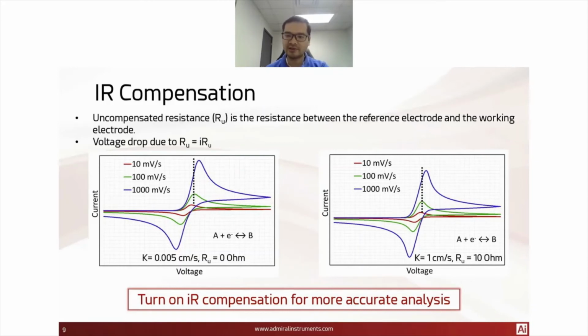So for example, in the figure on your right, you can see the reaction rate, k, is fairly fast, and you have 10 ohm uncompensated resistance. If you increase your scan rate, the current magnitude also increases. That means your voltage loss also increases. So in this plot, you can see there's a systematic shift in peak potential. Compare that to the figure on your left, where it's a very slow reaction, but there is no uncompensated resistance. But you can also see here that there is a systematic shift in peak position.